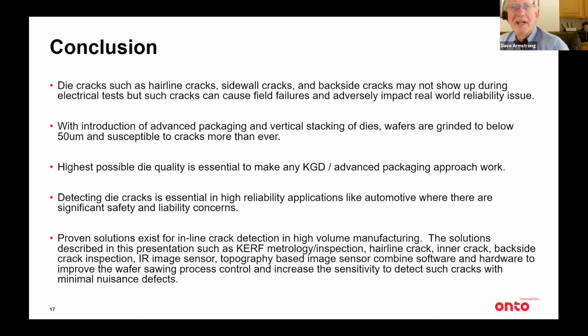Here's another question. I don't quite understand how kerf inspection can prevent the saw-induced kerf damage. Can you elaborate? Sure. So like I said, a lot of these cracks in sawing are initiated by the sawing process. And if you keep your sawing process so that the material being removed is minimal, as well as keep the sawing at the center of the street, right? That would be the best prevention for cracks to happen in the first place. As your blade gets closer to the die and deeper, and more material is removed, you're getting closer to making all these cracks.